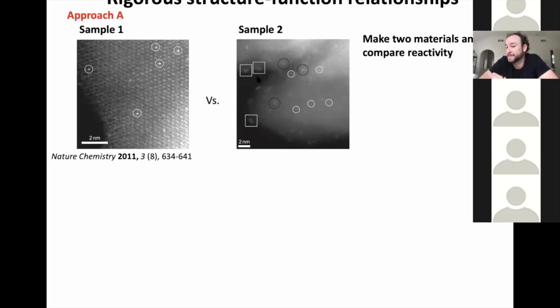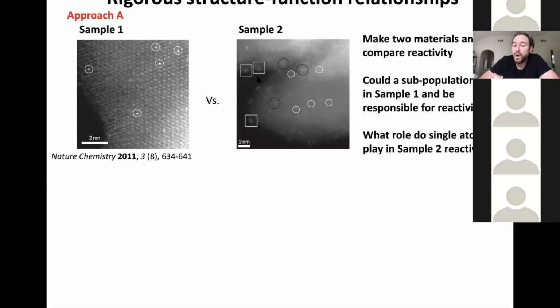So we can make two materials and we can compare reactivity. There will always be a question of whether or not there was a subpopulation of species in this sample, which were predominantly associated with the measured reactivity. And there will always be a question of what the single atoms that you saw in this sample were doing and playing a role in the chemistry, and how do you differentiate those? It's very difficult to do from just looking at two different samples that from characterization approaches have some differences in structures.